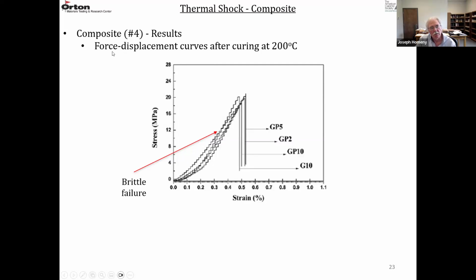So if you measure these on a mechanical test machine, you get the following type of force displacement curves. These are cured at 200. So you have GP2, GP5, GP10. These have the MgO carbon pellets, G10 doesn't. So they all exhibit this kind of behavior. It's a brittle fracture. You have linear behavior up till fracture and a rapid strength loss. So it's a brittle kind of material. That's what you would expect from the resin after curing.